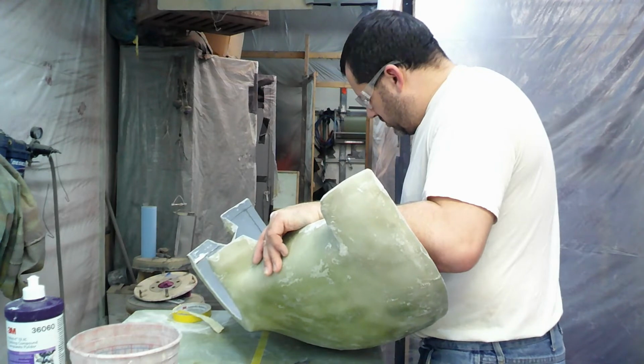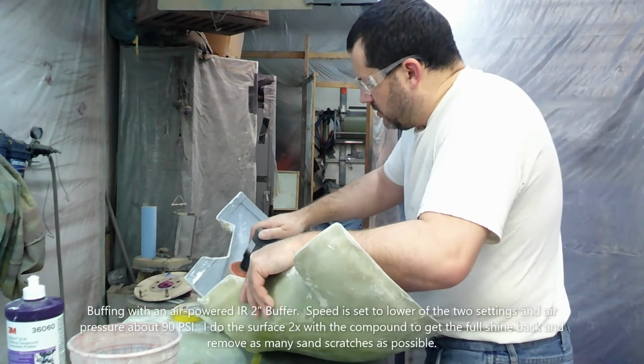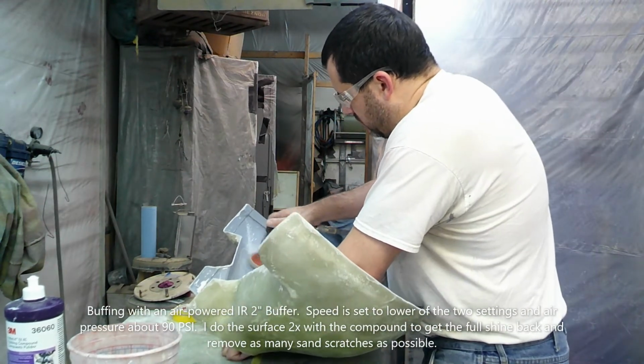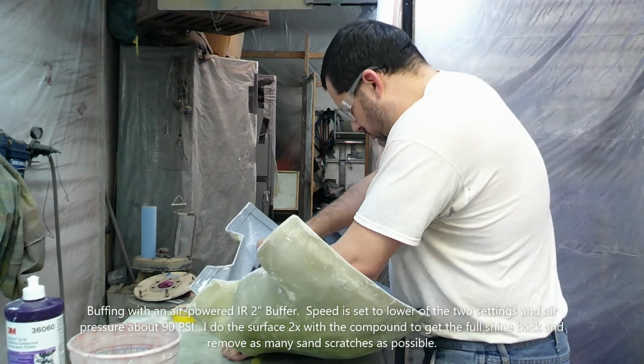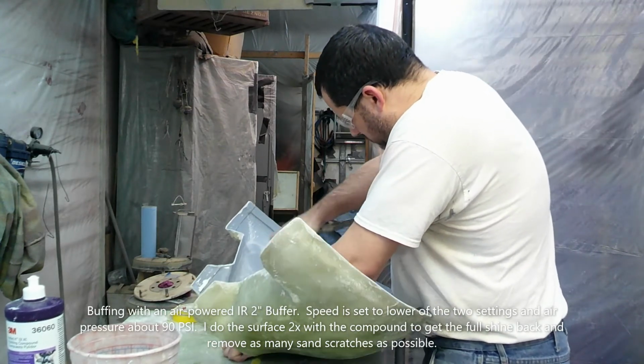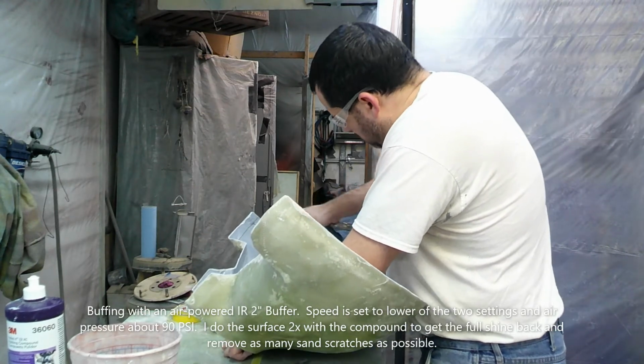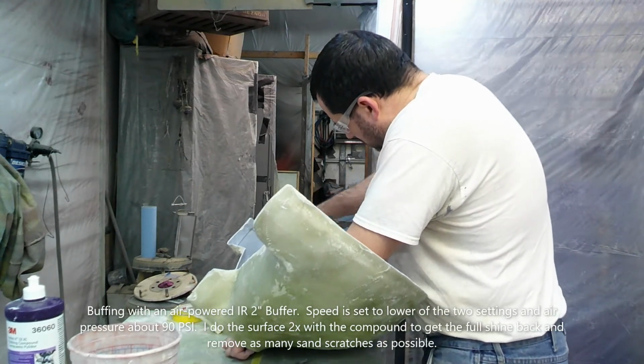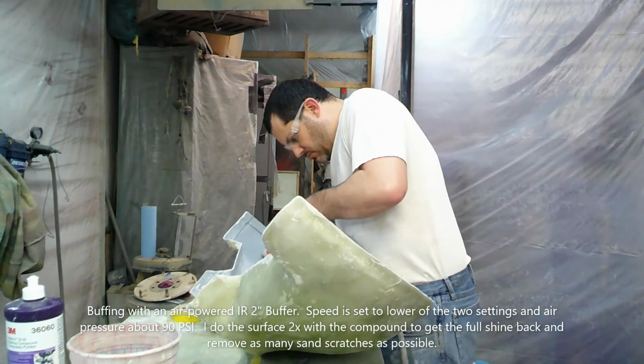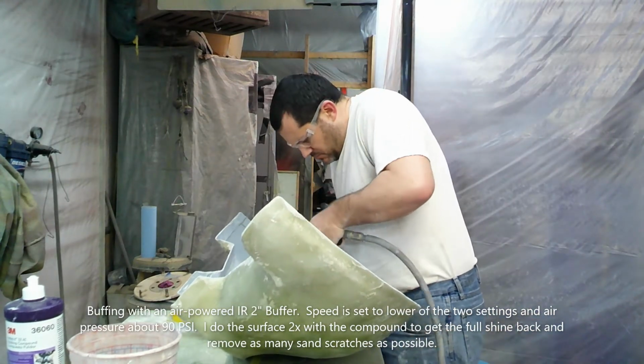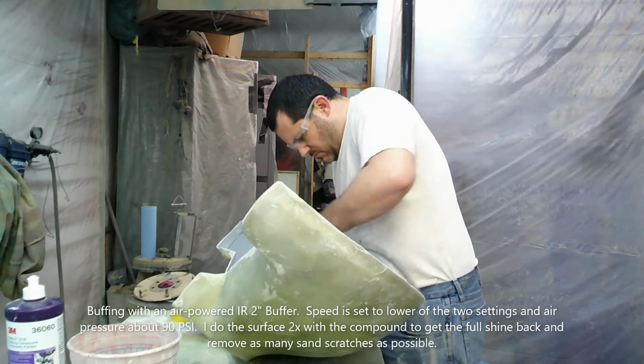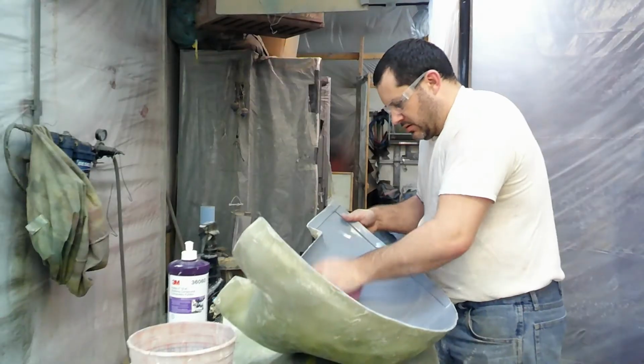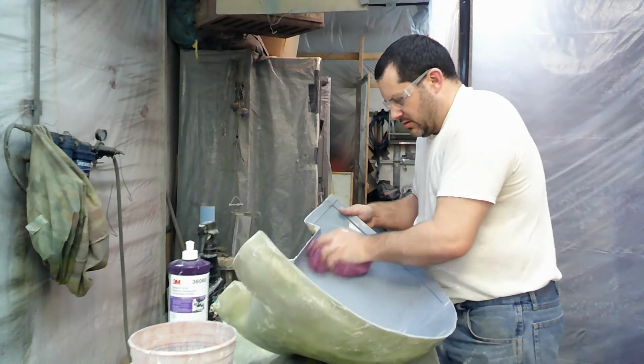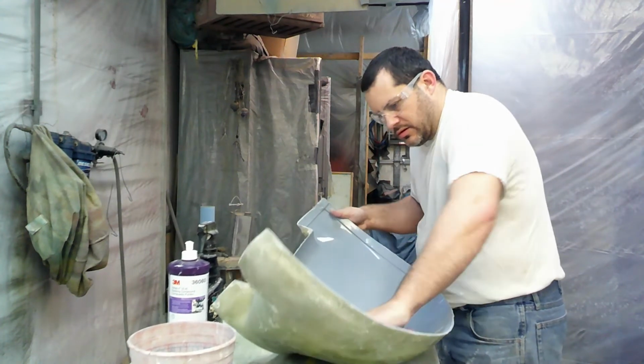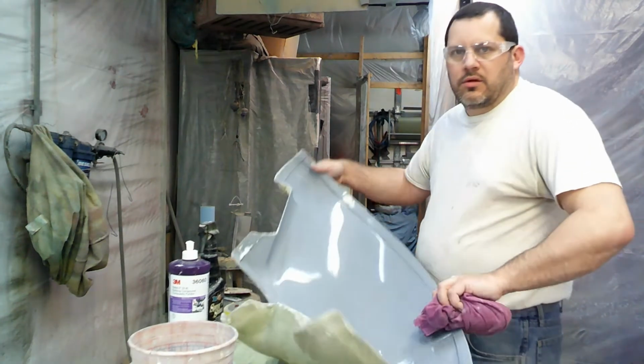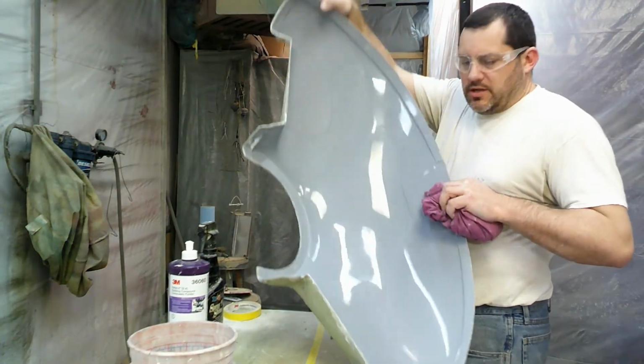Here I'm buffing with an air-powered Ingersoll Rand 2-inch buffer. The speed's set to the lower of the two settings, and the air pressure is about 90 psi. I do the surface 2 times with the compound to get the full shine back and remove as many of the sand scratches as possible. Pretty shiny, pretty nice.